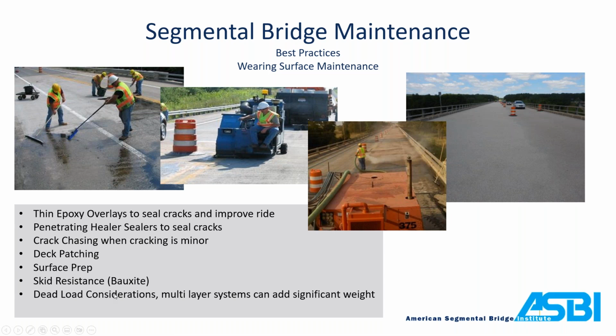If you're concerned with skid resistance, the bauxite aggregate is hands down the best aggregate you can use for long-term skid resistance. There have been numerous tests on this against other aggregates in the industry, and bauxite just outperforms all of them by a long shot.